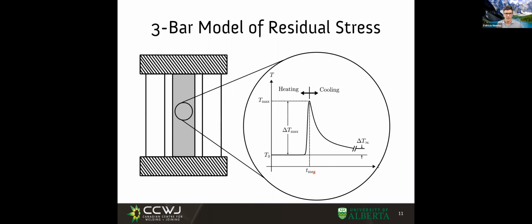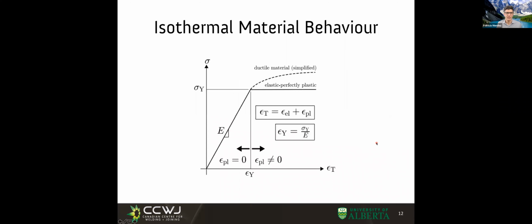Three-bar model. In this model, bar number 1 and bar number 3 are always at preheat temperature. Let's call it room temperature. Bar number 2 in the middle goes hot and then cools down. The material we're going to consider is elastic, perfectly plastic. So as we stretch it to a point, the atoms stretch, but then when we let go, it goes back together. And if we stretch it too much, it starts yielding.